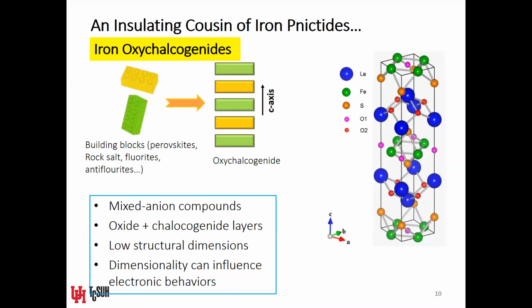So now I'm going to talk to you about a different type of iron insulator, one that's highly insulating. And this class of materials is known as the iron oxychalcogenides. They essentially are a layered structure. If you move along the C-axis, you have different blocks. You have a perovskite block, and then you have a fluorite block. The bottom line is you end up with two different regions. This is, for those of you who know about the cuprates, analogous to the rare earth oxide layer in a cuprate and the copper oxide layer.